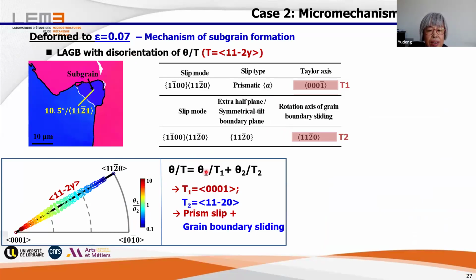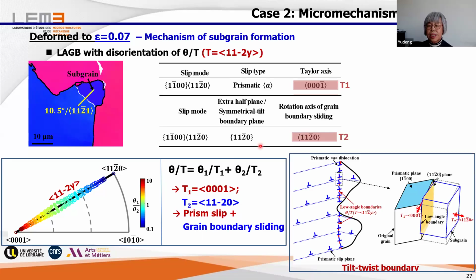You see, varying these two angles, fixing these two axes, we find the axis falls in this orientation line. And that means, and we made a further analysis, I have no figures to show here. In fact, the orientation, the trace of this boundary normal, is exactly parallel to this axis. And so this allows us to identify that during this process, there's boundary sliding.